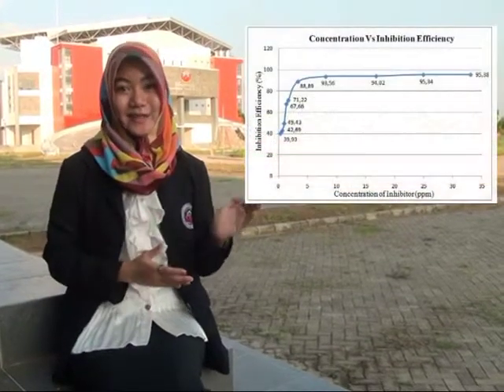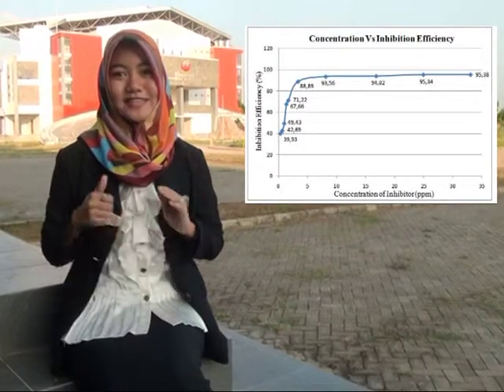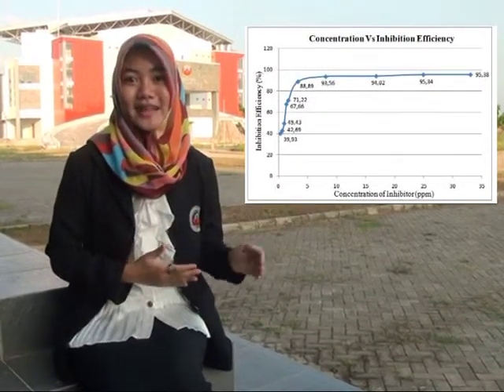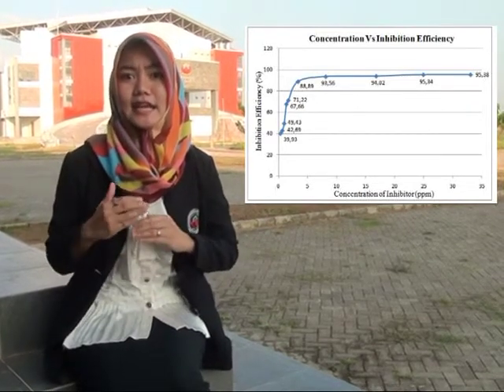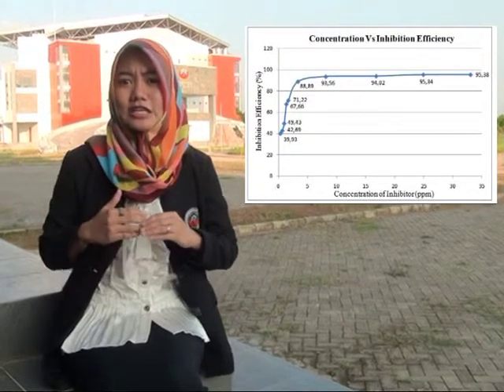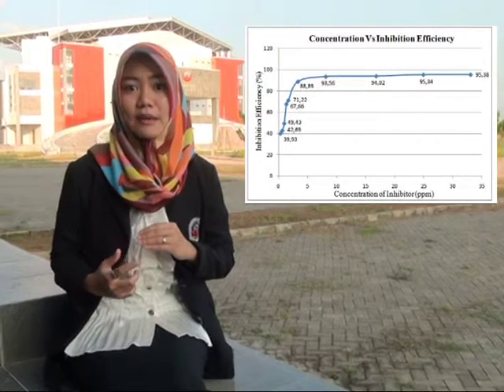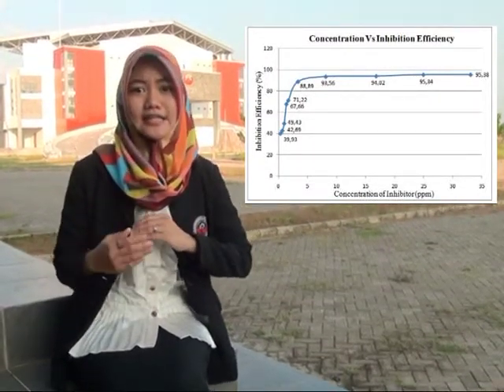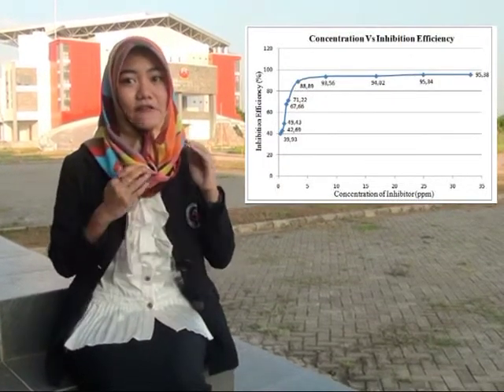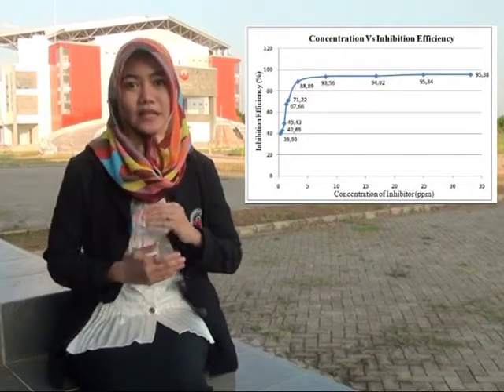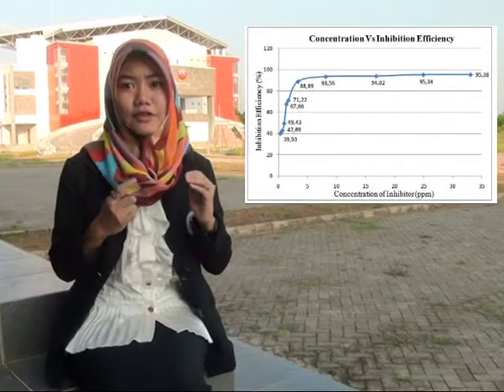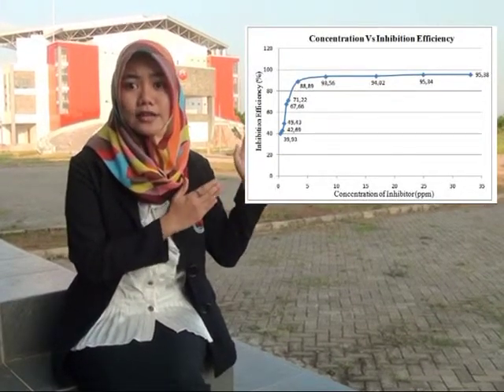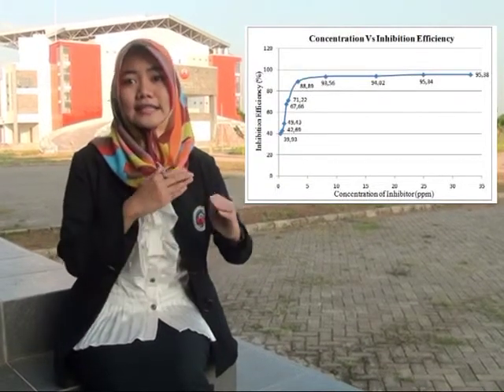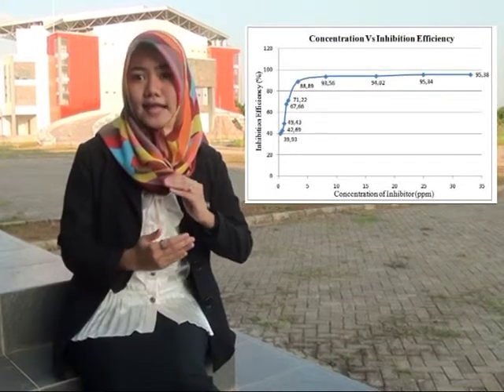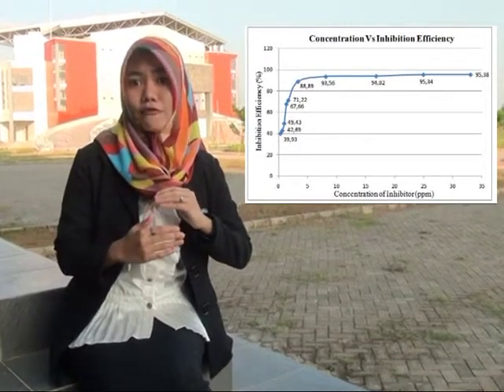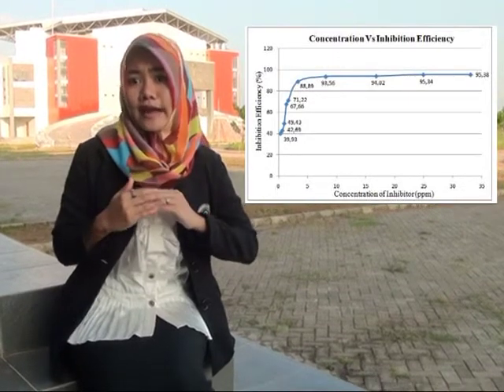The second chart explains the corrosion inhibition efficiency for immersion of 6 days. From the graph above, it can be seen on matte steel immersion for 6 days that the inhibition efficiency value increases with increasing concentration given. This is because of the effect of the given inhibitor concentration. The greater the concentration given, the greater the inhibition efficiency value. The greatest inhibition efficiency value is present at 33 ppm with a value of 95.38%,